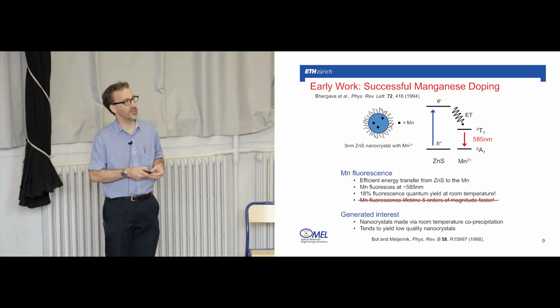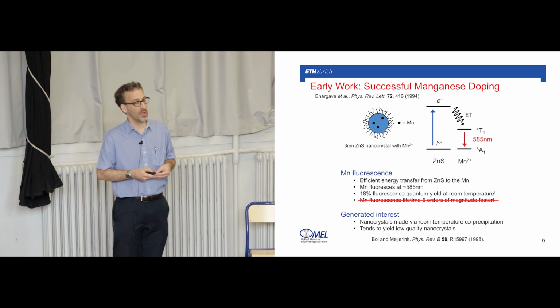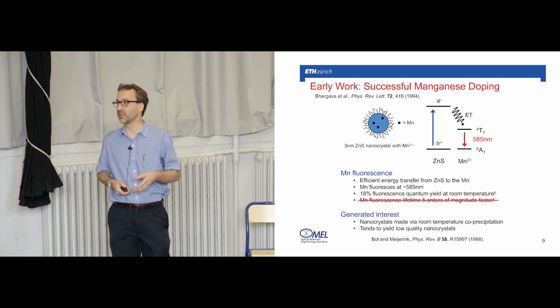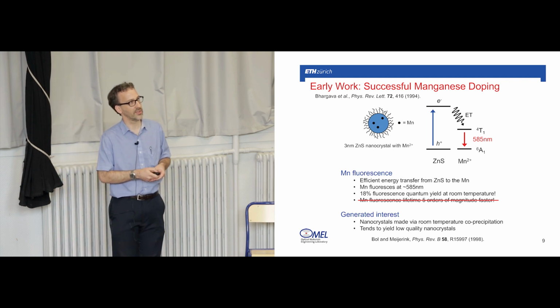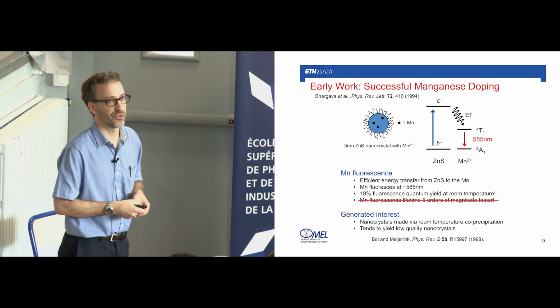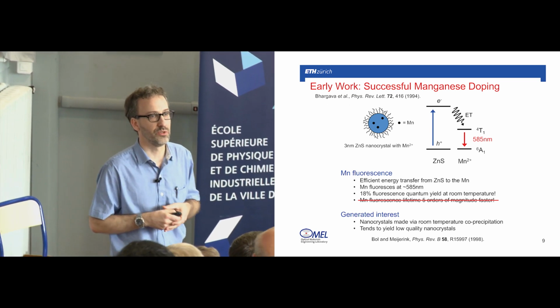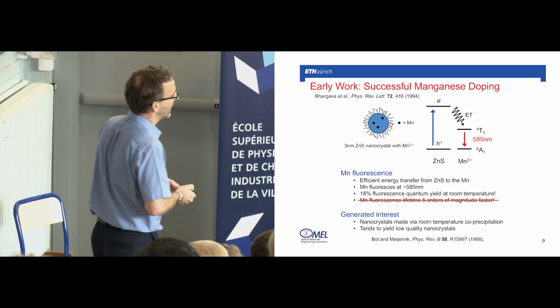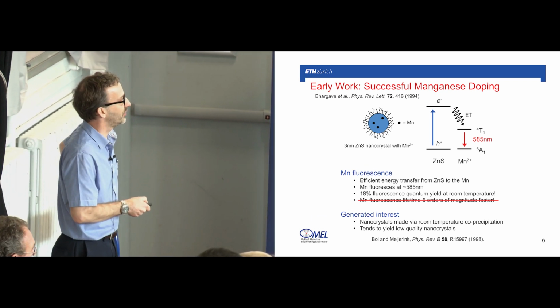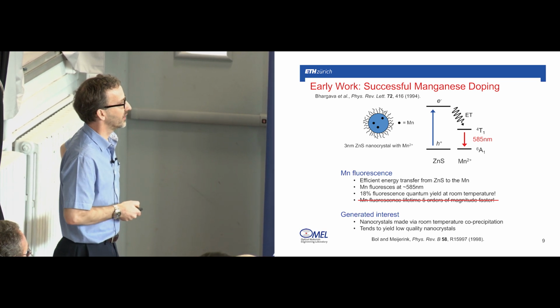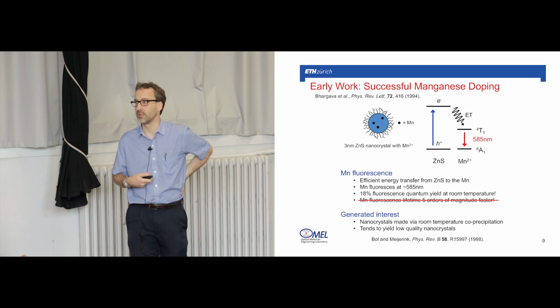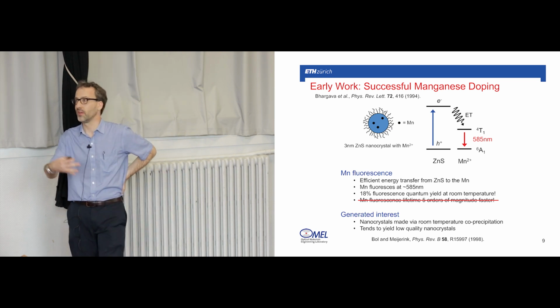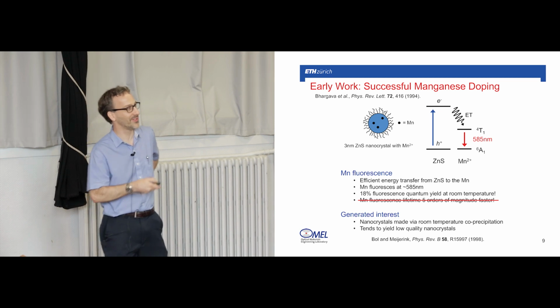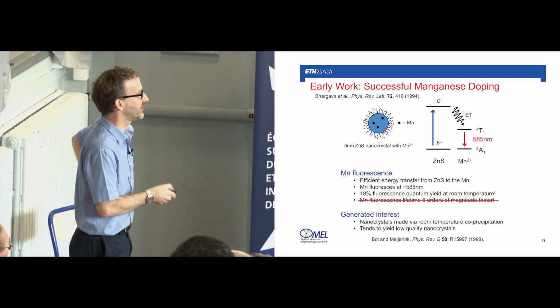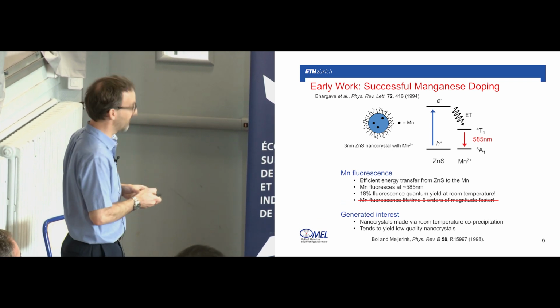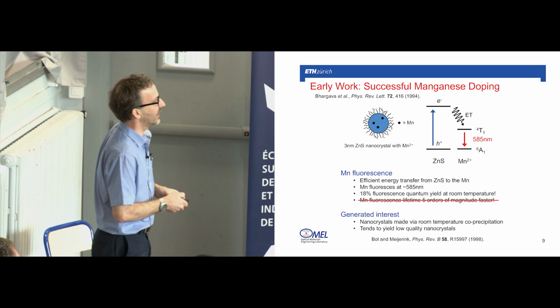Moreover, they claimed in this paper that the lifetime of this transition, which is partially spin forbidden, so in the bulk it's 2 milliseconds, a very slow transition, was 5 orders of magnitude faster in the nanocrystals. And this got everybody excited that this was unexpected and this was new physics. Unfortunately, our chair here, Andres, and his student proved a few years later that this was an artifact, and the lifetime was actually just as slow as it was in the bulk. But in some sense, the train had already left the station, right? People were already excited about all of this stuff, and the fact that this second exciting thing was not true didn't seem to affect that at all. So this generated a lot of interest.